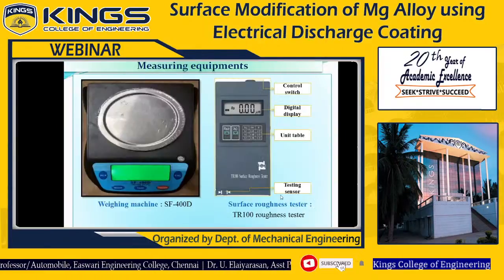Next, the measuring equipment used for our study. The SF400D weighing machine is used for measuring the material deposition rate. To calculate the material deposition rate, we use the before and after weight of the workpiece. Before conducting the experiment, we weigh the workpiece and electrodes, and after the experiment, we weigh them again. The difference between before and after EDM is the material deposition rate. The deposited workpiece is also analyzed using a non-contact surface roughness tester, a TR100, to measure the surface roughness value, which is also available in the university.